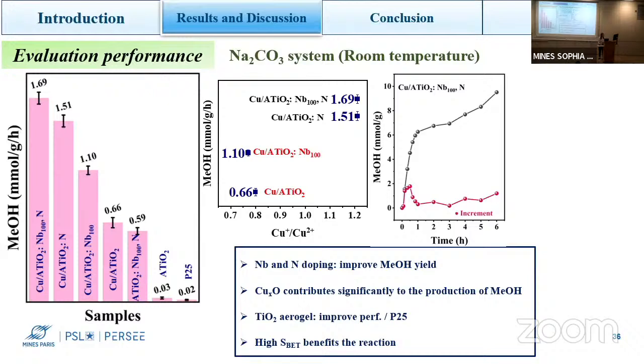Yeah, this is because after this result, I can say the surface with more copper 1, even with more copper 2, gets the better performance. That means copper on the surface improves the catalysis, but in our in situ case, most of the copper is in the bulk, not on the surface. So we try to use the impregnation method to put more copper directly on the surface. Very nice. Sorry, I didn't catch this point. There is some hidden or not accessible copper, and you want to increase this accessibility, and finally you change completely the synthesis work. Yes. Okay, very good, very good.